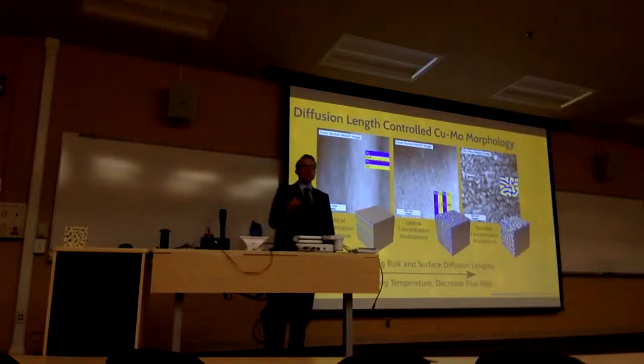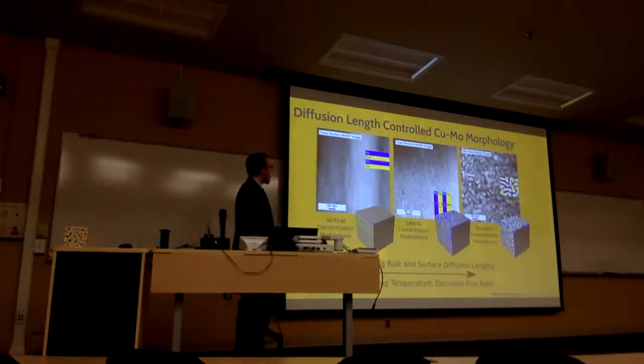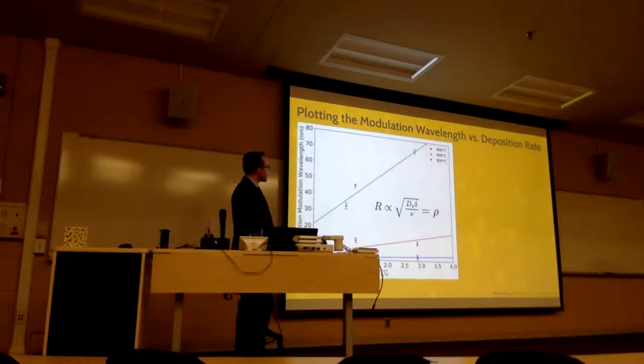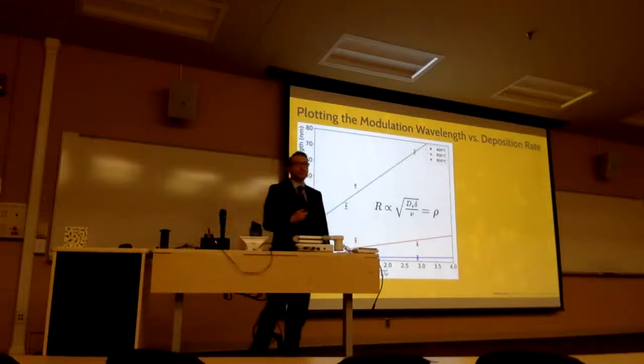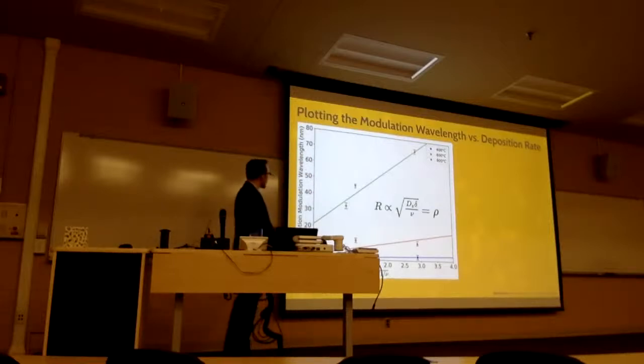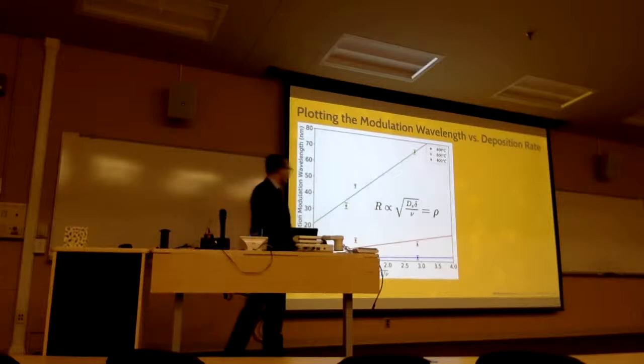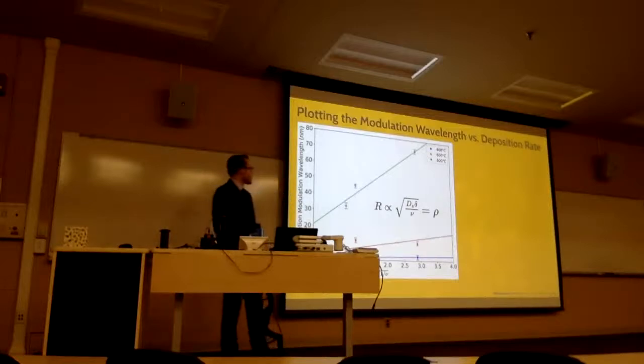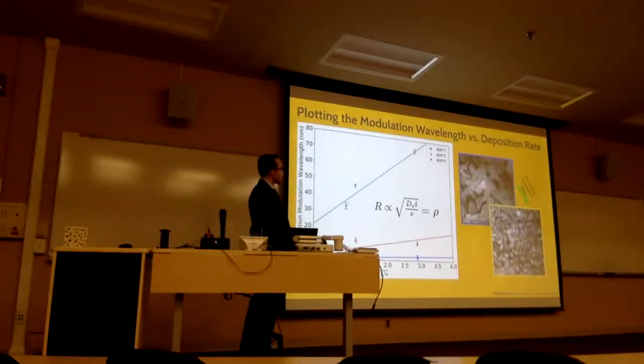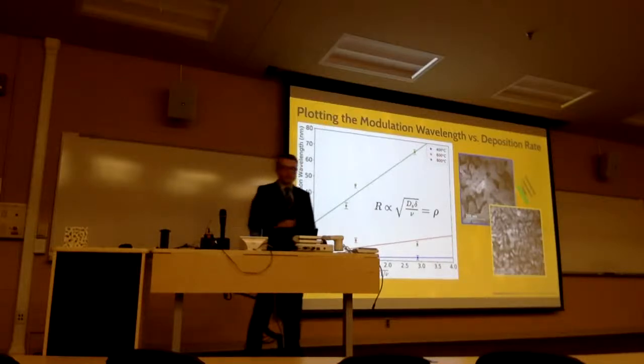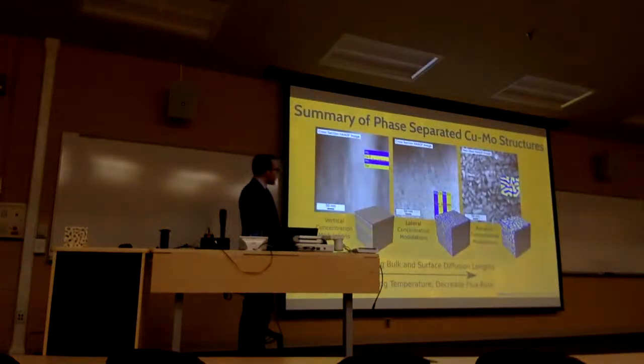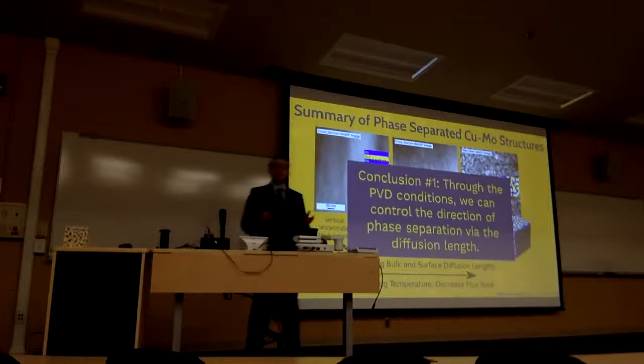And so we wanted to match up our empirical results to the analytical model put forth by Dr. Michael Betzman's group. So what we did is we saw this relationship once again, and it describes the domain size proportional to the square root of 1 over the deposition rate. So we tried to map out, again, that R value, or concentration modulation, as a function of the square root of 1 over domain size, or deposition rate. And we saw that our experimental results actually match well with what was predicted by this model. And experimentally, we can show here that at a particular temperature, 800 degrees C, by increasing the deposition rate, we can actually refine the structure in the sample. So we can see that this model actually describes our system and our empirical results. So in conclusion, through the PVD conditions, we can actually control the direction of phase separation by controlling that diffusion length in the sample during deposition.